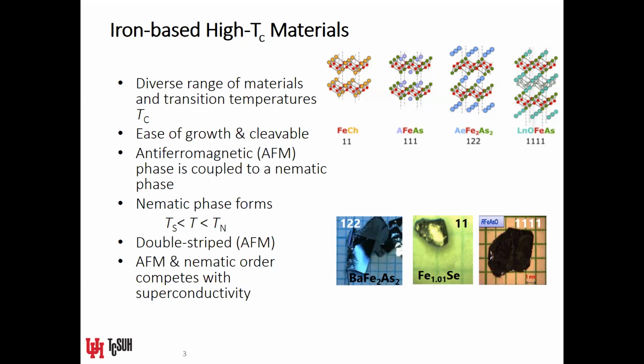Now, this nematic phase is essentially a C2 symmetry state in which the translational symmetry of the crystal is preserved, but its rotational symmetry is broken. Most of the iron-based superconductors in the normal state have a tetragonal symmetry, and so that's a C4 symmetry, a fourfold symmetry. If you go around the iron plane by 90 degrees, you'll end up in a symmetric position at every 90-degree interval. The nematic phase breaks that fourfold symmetry and results in a twofold symmetry, such that if you go 180 degrees around the iron plane, then you reach a symmetry-equivalent position. So you have a twofold symmetry in the nematic phase.